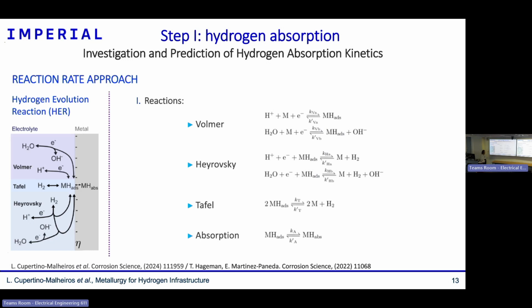So first, you need to identify what are the main electrochemical reactions that happen at the metal surface when exposed to an aqueous electrolyte. So hydrogen comes here from an electrochemical reaction, a reduction of either water or a proton. Then you have lots of hydrogen that will be adsorbed here at the metal surface. A great part of this hydrogen will just desorb, either chemically or electrochemically, and a small part will enter the metal. That's the part that we call absorbed and is related to hydrogen embrittlement.